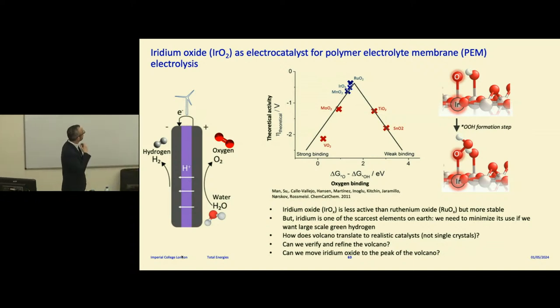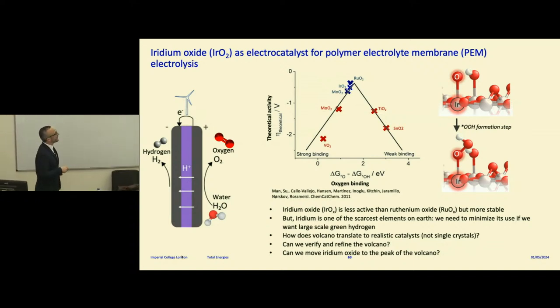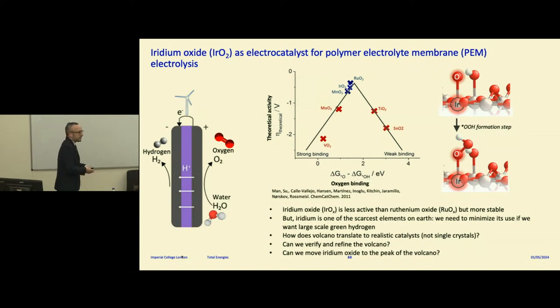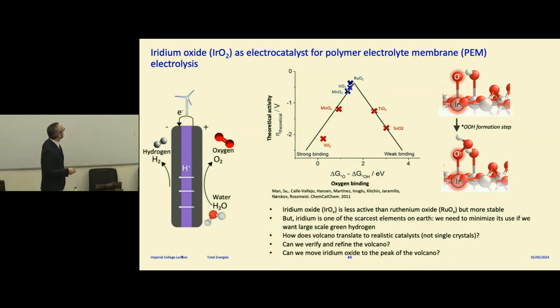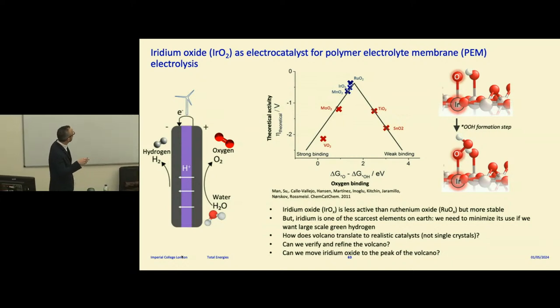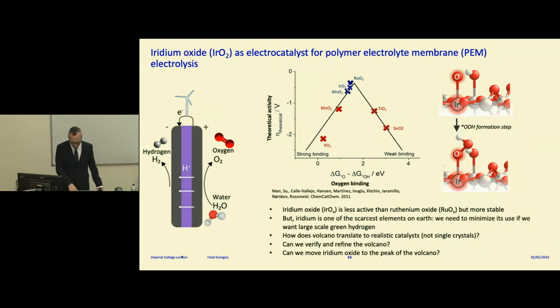There's a lot of talk now about making hydrogen at scale, but we're not going to do it if we use current technology. Often when we look for new materials, we just discover them by serendipity, and that's the standard way to do it, but we'd like to be more intelligent and do it by design. So we have this volcano, which in principle is a design principle. I've shown previously the volcano translates well for single crystals, but how does it translate to realistic catalysts? Can we verify it? Can we refine this volcano? And can we move iridium oxide to the peak of the volcano so we can minimize the amount of iridium that we use?